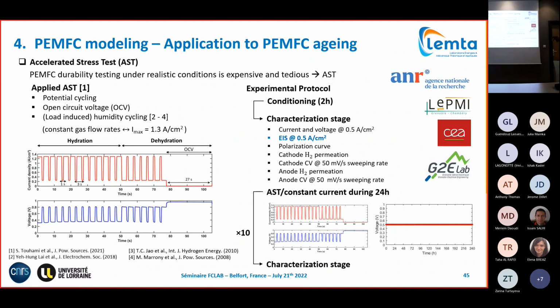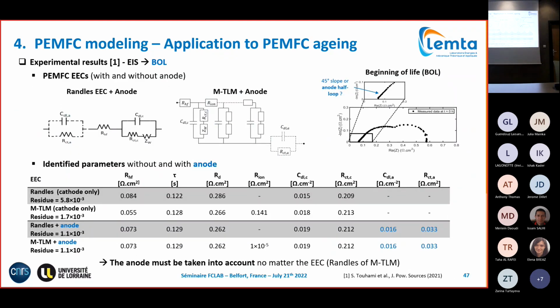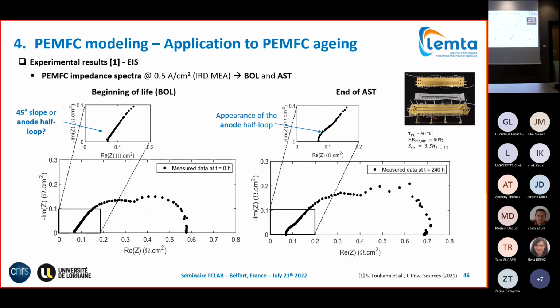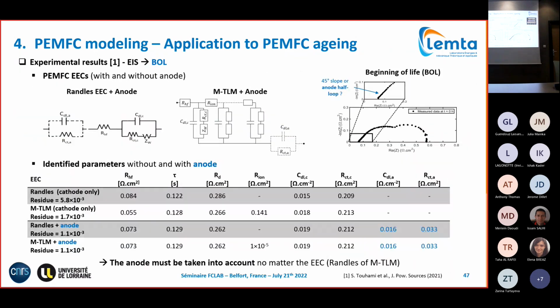Okay, just to be sure, this is done during 10 days, and every 24 hours this will induce stresses and create aging. Every 24 hours, we stop the cycle and make a characterization set. I think we measure performances. And then we use our model to interpret the spectra. Here I show you the spectra measured at the beginning of life and end of life. Every 24 hours we have one spectrum that we fit with our model. Our model allows us to identify the evolution of the high frequency resistance, which is linked to the membrane. So this gives us information about the state of the membrane.